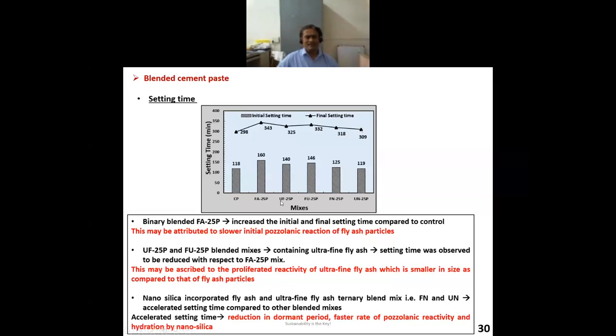The moment I replaced 25% fly ash, you can see the initial setting time increases by 42 minutes. And we know that is natural. The moment you add fly ash, the hydration process goes slow, and we know that very well. But see, the setting time keeps reducing the moment I go with the secondary cementitious materials.